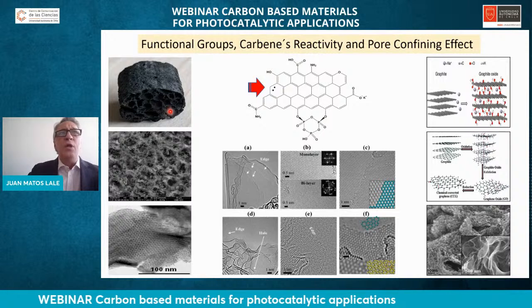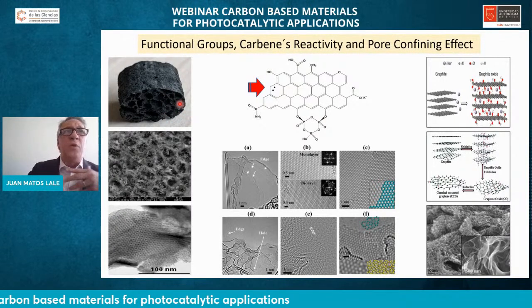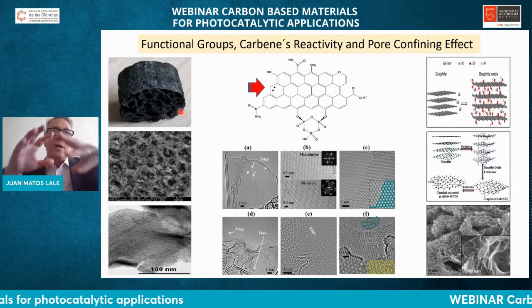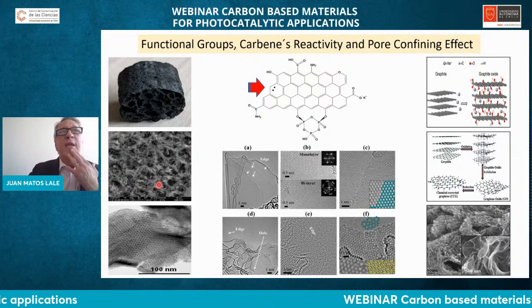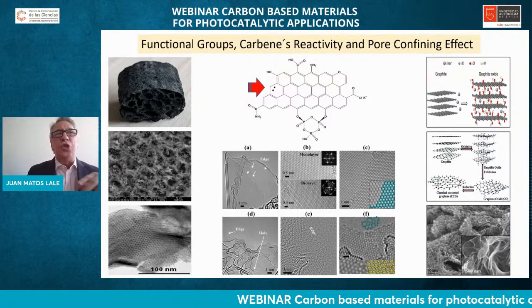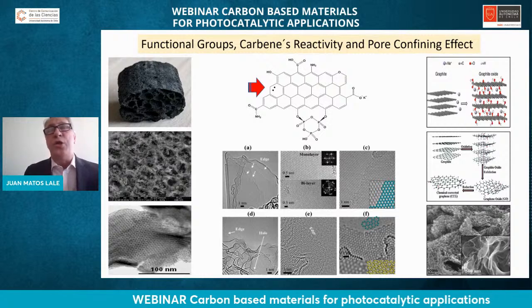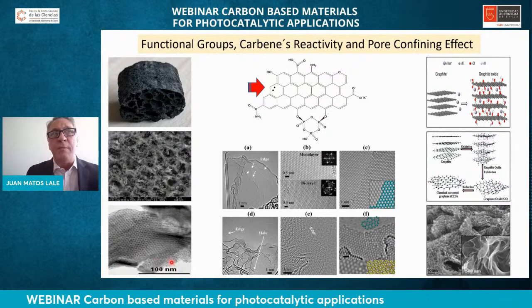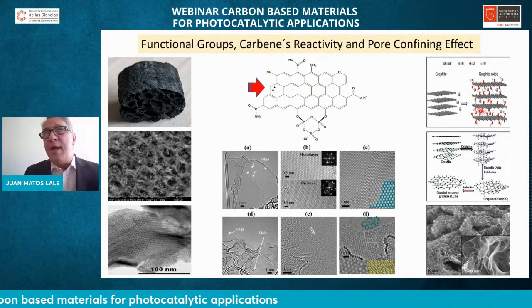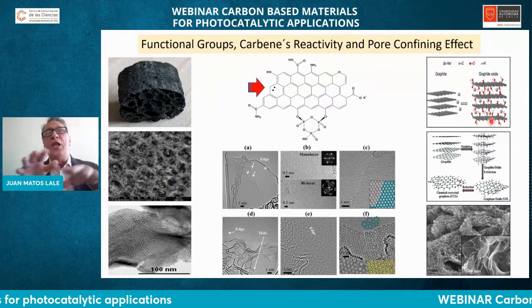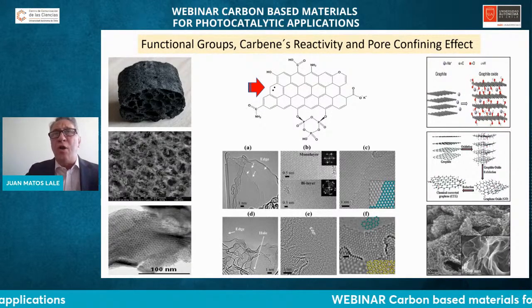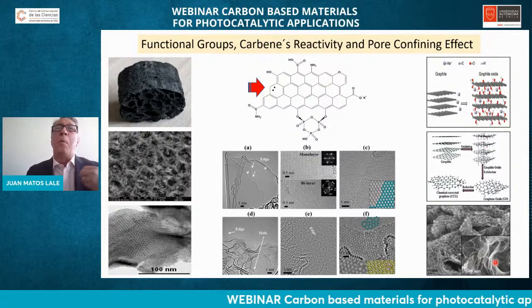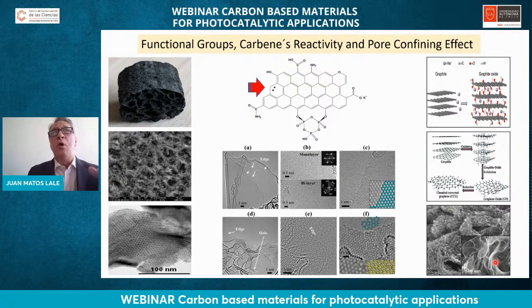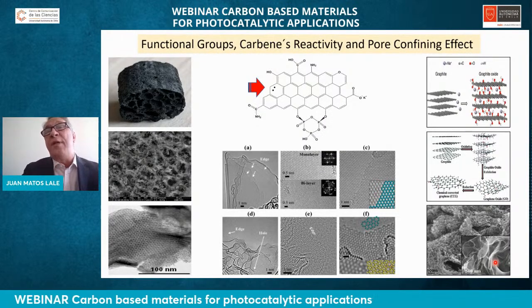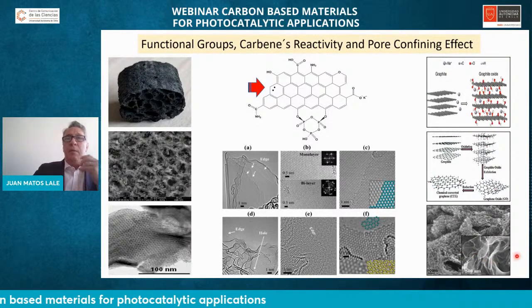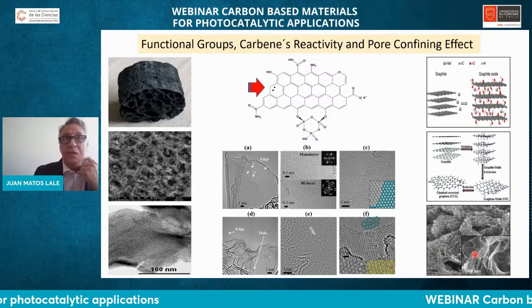We can control the geometrical forms, in the kind of monolith, a kind of cake of carbon. We can control the pore size distribution. We can control the topology of the pores in the shape of pillared mesoporous carbon. We can control the exfoliation, the intercalation. We can even promote the formation of what we call graphene-like foams, as in the bottom right part of the slide.